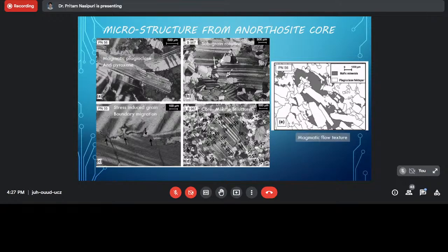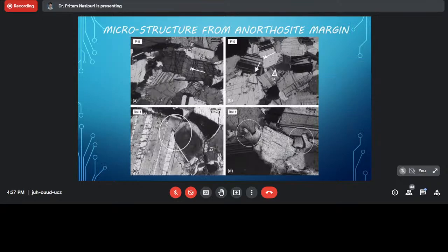Now, if we come to the anorthosite margin, you can obviously see the grain size changes rapidly. First one is the pyroxene, which shows a kink band, and pyroxene kinking is a very important, very high temperature phenomenon, and it occurs mostly at temperatures greater than 900 degrees centigrade. Again, if we see the plagioclase crystals, they roughly show an alignment. The best way is to see that the albite lamellae are mostly parallel.